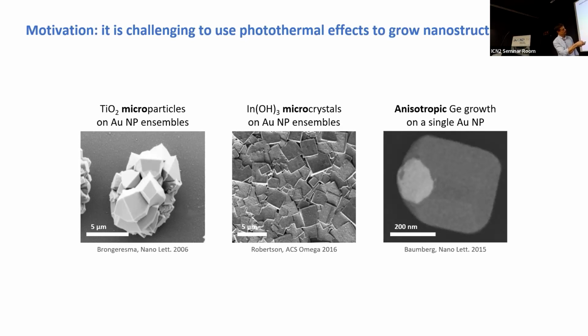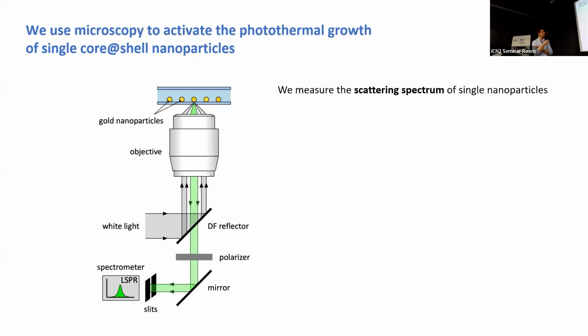Here there is a little gold nanoparticle, not so little, and this is germanium that is growing on top of it. Some of the problems were that typically these structures were very large. There was no fine-tuning of the nanomaterial synthesis at the surface. It was unclear whether this was a purely photothermal or an electronic process. And so we wanted to develop a strategy to be more controlled and actually study this process in real time. And so our approach was to use microscopy to activate the photothermal growth of a core-shell nanoparticle.